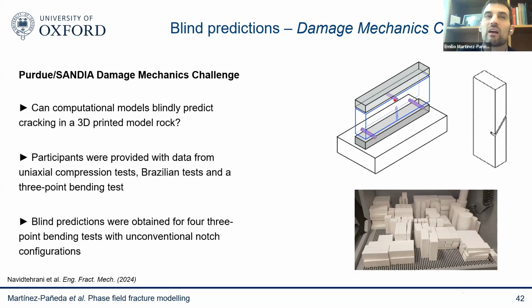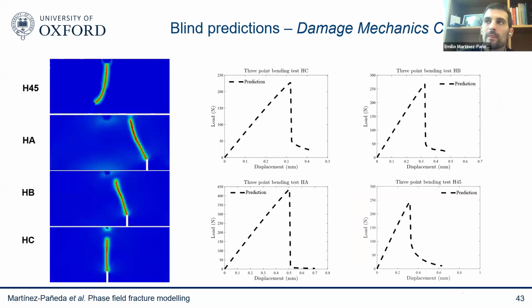So I'm not surprised that models that have a lot of parameters are able to fit experiments because, you know, if you see an experiment and you can calibrate many parameters, that's not a surprise. But the ability to blindly predict experiments with as few parameters as possible, this is what I think makes phase field very powerful. And so then basically they said, okay, now we want you to tell us the output of three-point bending tests that are basically unconventional notch configurations. And they have DIC data and they have force displacement curve data that they didn't give us, and also XCT data.